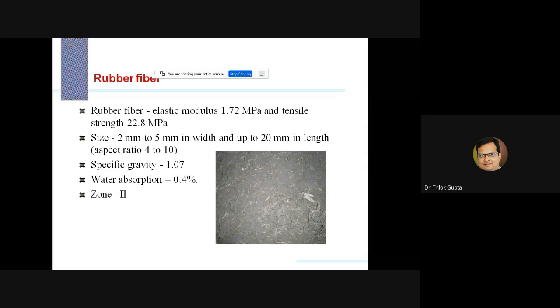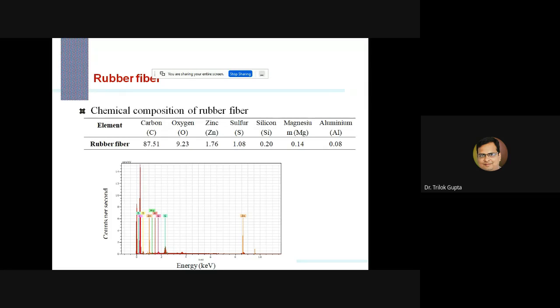Tensile strength was 22.8 MPa, whereas the width was 2 mm to 5 mm, and the length was around 20 mm. The aspect ratio was 4 to 10. Aspect ratio is the ratio of length to width or diameter. Specific gravity 1.07, water absorption 0.4, and it lies in zone 2. There was a higher percentage of carbon because there was no heating process, so the carbon content was 87%.